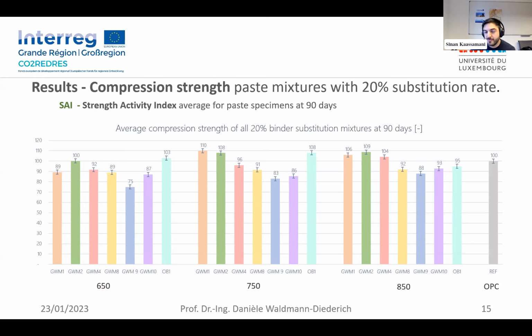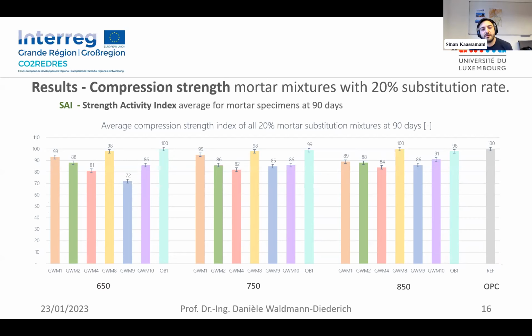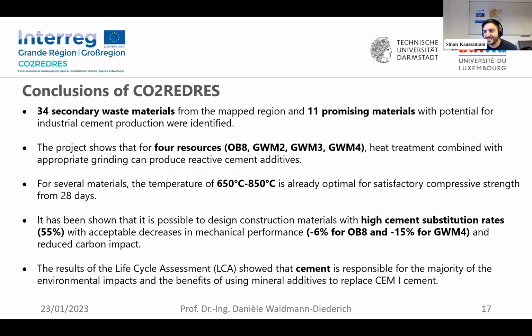And so this is for binders, and then also for mortars, we had similar values of around 70 to 100%. And as we can see, almost all the materials that we studied are promising. So I give back the stage to Professor Waldman for the conclusions.